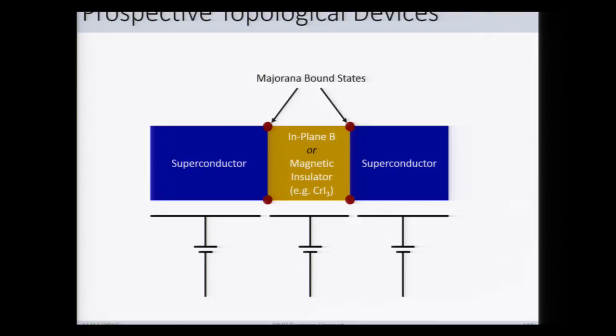And what we can hope to do is, by using an in-plane magnetic field at very low temperatures, induce a gap and an insulating phase in the helical mode here, but also preserve the superconducting state on either side, and maybe realize Majorana bound states at these corners, which can potentially be inspected via some sort of spectroscopic tool.